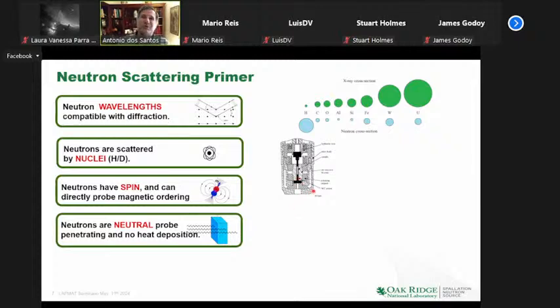Another thing which is also important for the neutrons is that they don't interact so strongly with materials, so they don't deposit heat. For instance, in X-rays, as soon as you shine a synchrotron on a protein, you basically decompose it instantaneously. You can do neutron measurements on the same protein over days without any effect. The same thing is true if you want to do studies at millikelvin temperatures with neutrons: you are pretty sure it stays at millikelvin temperatures, which is a challenge for X-rays, because you don't really know the local temperature where you're illuminating, since X-rays will warm up your sample.